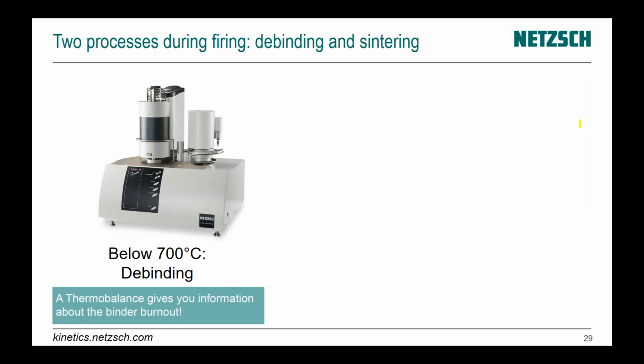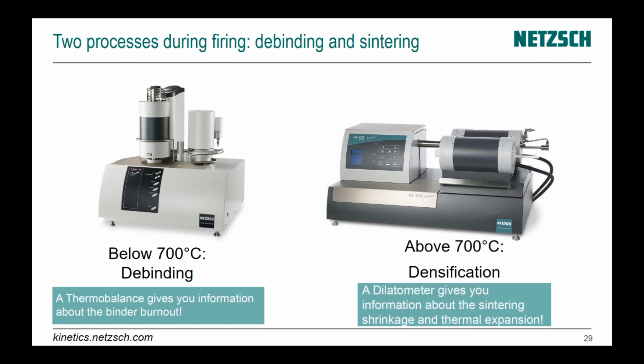During firing of ceramics, there are two processes. One is below 700 degrees C, it's debinding - decomposition of polymer - and another above 700 degrees C is densification, which could be measured by dilatometer.